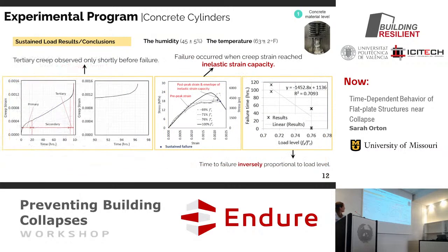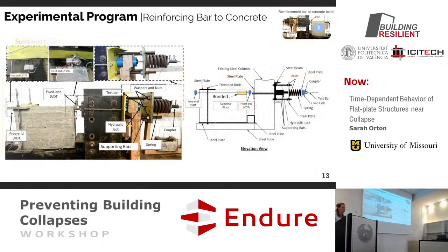And the specimens that failed, there was definitely a tertiary phase where there was a sudden increase in strain right before failure, and it occurred in a fairly short window right before failure. And then this curve is my static compression test curve, and the ones from the long-term tests, you went up here, sustained loading, and then they failed when it hit the descending branch. It worked perfectly. This other one that went up here was the 69%. We needed to reload it and cause failure, so that was a little bit different. And otherwise, the data worked out. We can see the time to failure is inversely proportional to the load level. We have a good understanding of the concrete material.